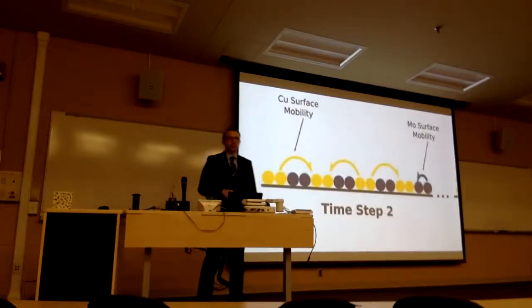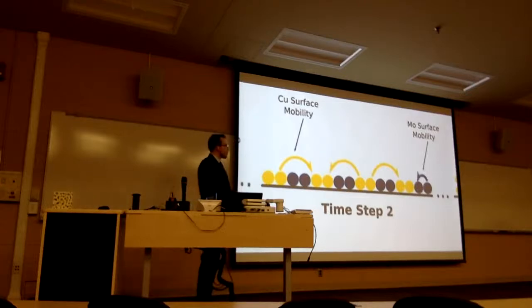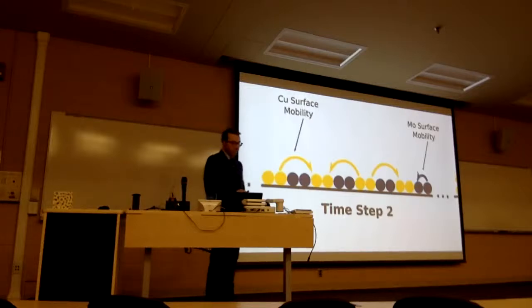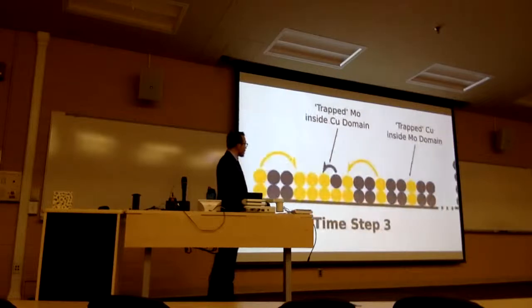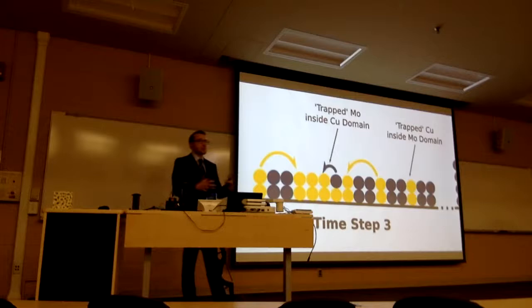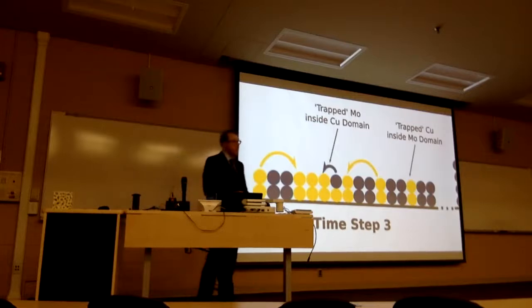As this structure starts to build up, we can see it attempts to form an LCM-like morphology or phase separate, but the copper adatoms can jump or travel much farther than those blue, slower mobile species. What starts to happen is that because the system prefers to demix, we have an agglomeration of copper in the structure, and any moly that gets deposited inside of that domain can't travel outside of it, and that's what we think is giving rise to those pseudomorphic moly precipitates inside the structure.